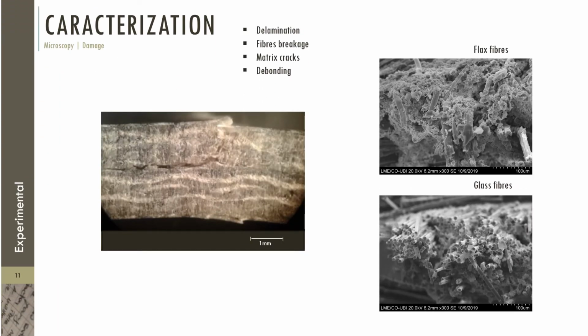The microscopic images show us the typical damages that we have in our composites. We can see that there are some delaminations and fiber breakage here in the compression zone. In this fiber breakage, we can see that there are some differences between flax fibers and glass fibers. We can see in those images here on the right.